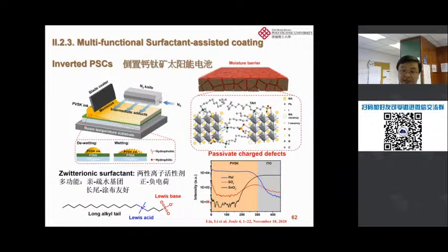time-of-flight SIMS. Okay, this tells us where these surfactants are. Then we can see that it's actually close to the surface. Okay, they like to be on the surface of my perovskite film. But at the bottom, you still have another enhancement there. That agrees with the scenario that the long chains point outside on top and point downwards. Okay, so that tells you it can actually protect your perovskite on both top and bottom, although at different degrees there. Okay.